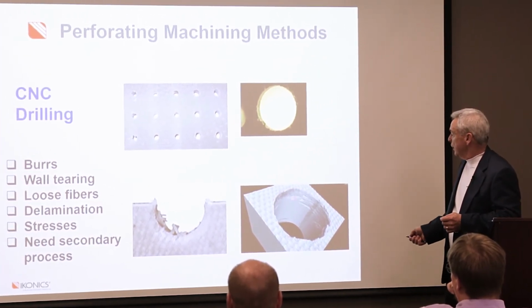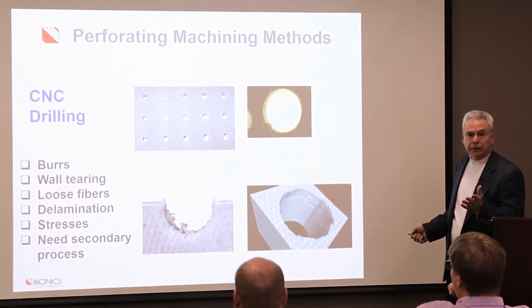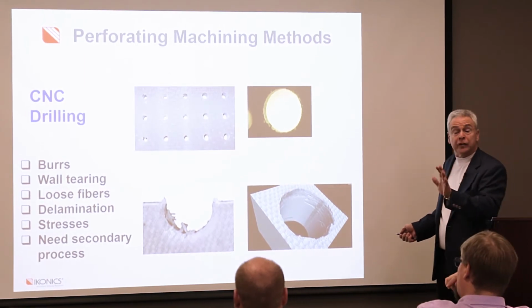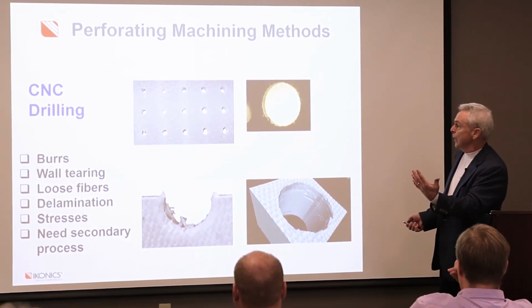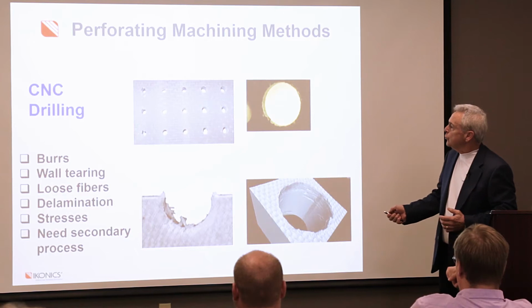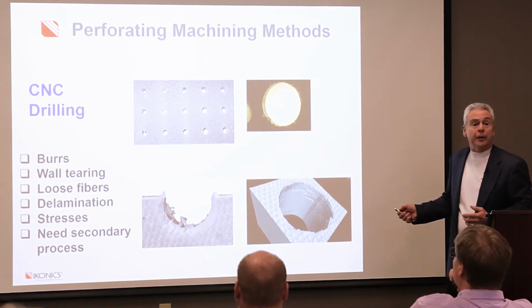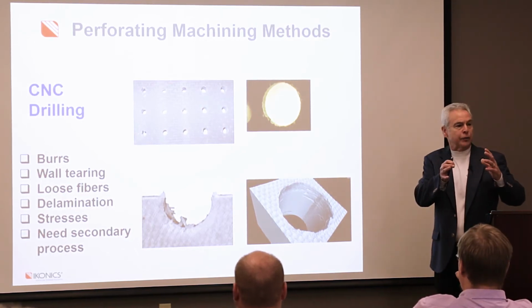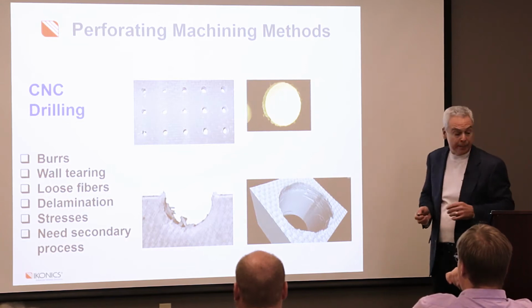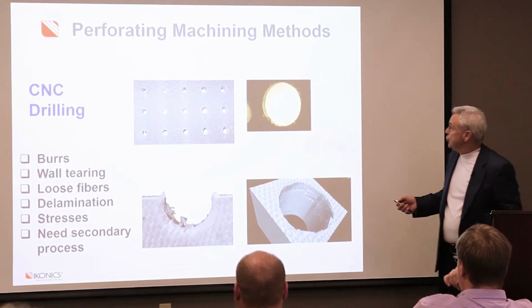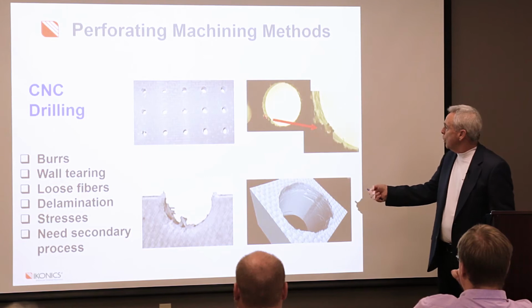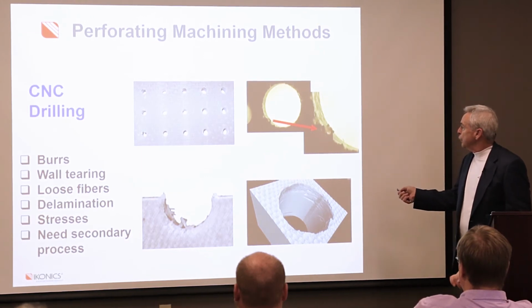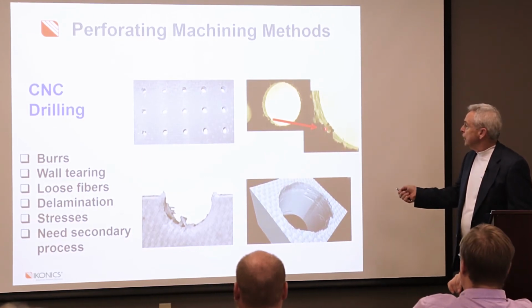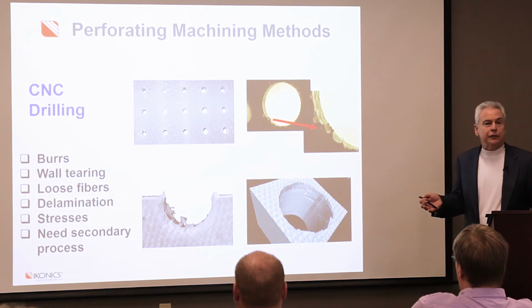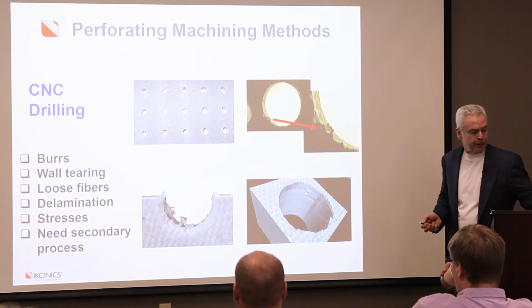You'll see here there's tearing of the wall inside of the hole. A lot of things you don't see necessarily unless you're looking under a microscope. And as the drill wears, you start to see this uniformity problem where the actual hole sizes will vary and change over time. Now, this is just showing a close-up of that sidewall, and you can see the burrs and the loose fibers that exist in here. And again, you don't see that until you're looking under a microscope, okay?